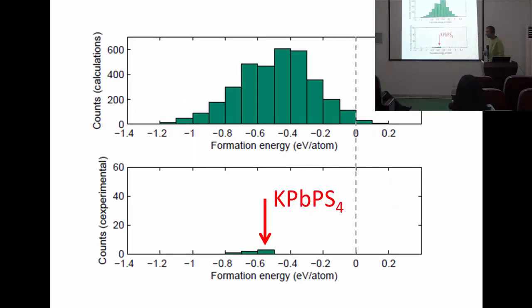Now, we can make a histogram out of that. I can take all my about 4,500 crystals that are in this set. I can plot their formation energy as a histogram of the formation energy. And you see that only a few of them are really unstable against elemental decomposition. And if I look at the 6 known ones, the 6 that were experimentally discovered already, they have formation energies in this region. So this potassium lead phosphor sulfur is there with a formation energy of about -0.6.